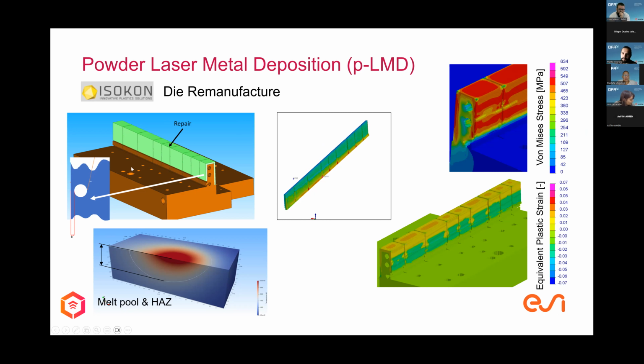So we looked into different options, how to deposit material on these surfaces. The strategy is shown here. We print on one side, then the other, and then we close on the top. And here we look at the melt pool size as well as the heat affected zone. We are most interested in the dimensions so that we do not melt the remaining material away. Yeah, it has to stay there. So that we can deposit metal on it.